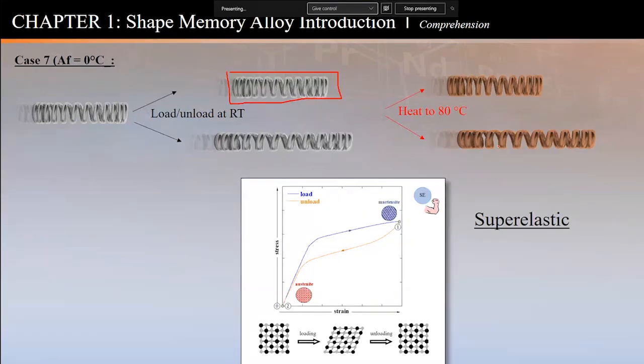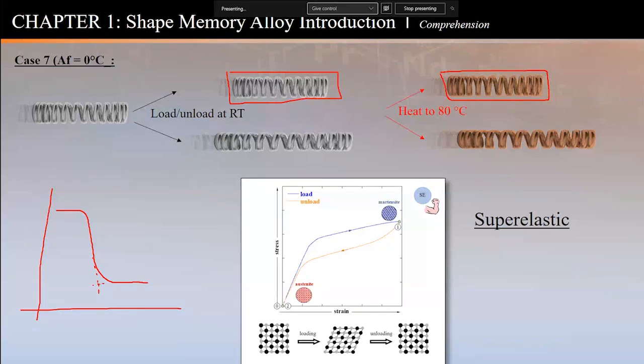So I'm going to do my best to sketch it over here. Hopefully you can see this. So here's my curve, the heating curve. I said my AF is over here, and I'm at room temperature, so I'm pulling over here. I'm deforming over here, so I'm past the transformation. Even if I heat up and I come here, nothing happens. So it stays the same way because I'm done. My transformation is behind me. It's all done. That's what this exercise shows us: if you are above the AF, you're going to see superelasticity. And if you increase temperature, you don't recover shape because it's already recovered. You don't get any dimensional changes.